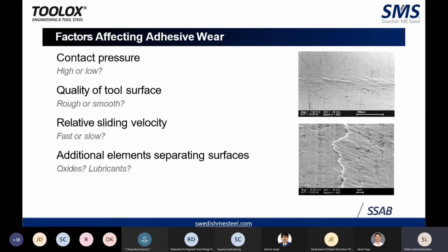The main important factors are the contact pressure, so you can check whether your pressure is high or low; the quality of the tool surface that you use, whether the tool surface is rough or smooth; and relative sliding velocity, whether it is too fast or too slow; and additional elements separating the surfaces, the kind of oxides and lubricants that you use. So these are some of the areas where it is affecting your wear.